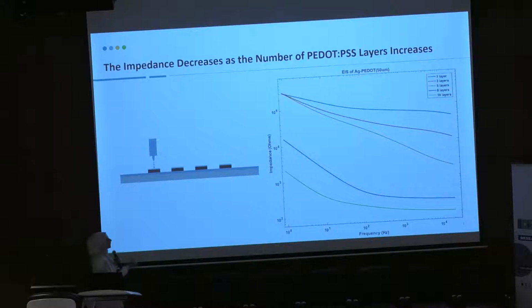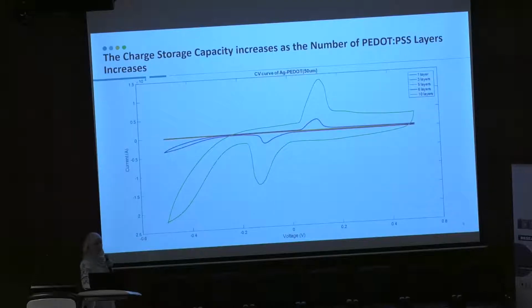So here we have different layers of PEDOT:PSS, and we showed how the impedance is dropping as we increase the number of the layers of the PEDOT. Not only this, but also the cyclic voltammogram, which is a measurement of the ability of the electrode to inject current, shows that the charge storage capacity increases as the number of PEDOT:PSS layers increases.